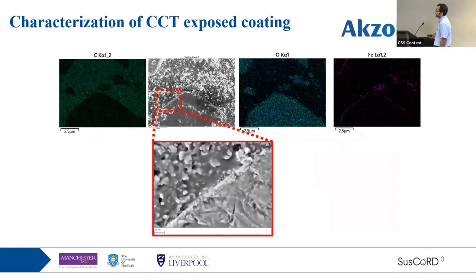And again, at this region, I can see from the EDS elemental maps that corrosion product and iron is deposited at this interface, but by looking at this, I couldn't see any gap. So it may also indicate that there are some paths within the polymer, or a combination of the two hypotheses that exist. But which one is true? I think we need to do more work. We are not clear on that.